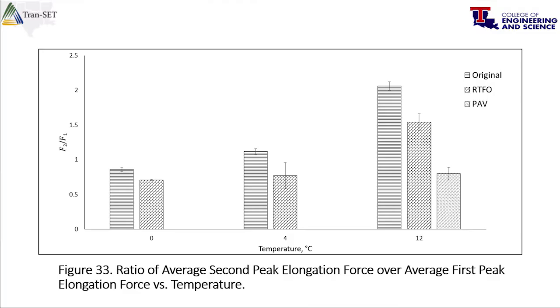And then I'll move directly to this one because I don't have time. This is 0 degrees Celsius. You can see that for the original binder, F2 over F1 reduced. At 4 degrees Celsius, it reduced. And at 12 degrees Celsius, we are just changing temperature to see if the trend holds. But I can always show you that as you increase temperature, the polymer effect is more visible. No matter if you do DSR or extensional deformation, the polymer effect, if you would like to find it, is more visible at high temperature.